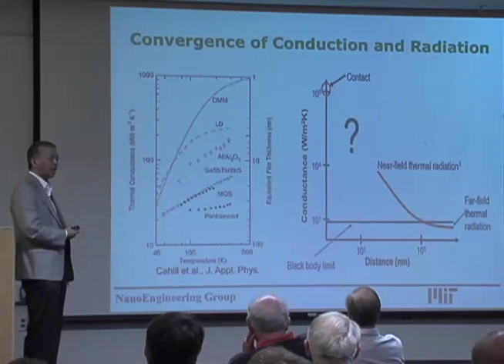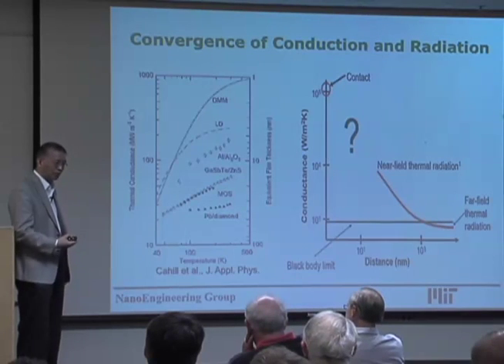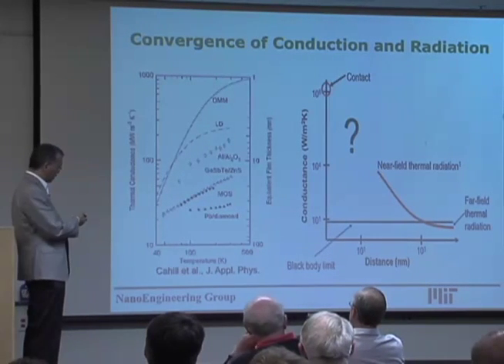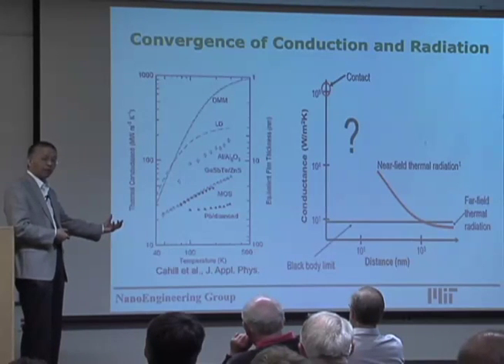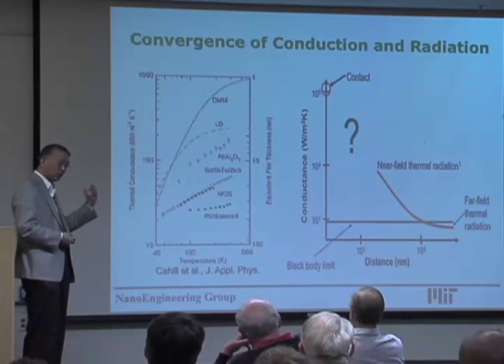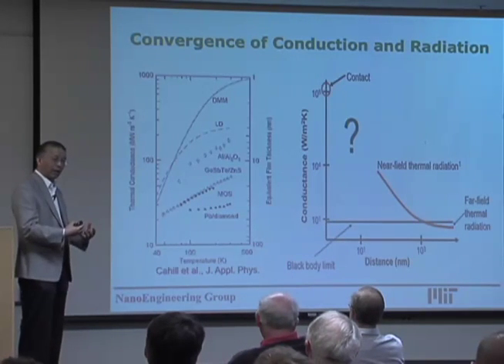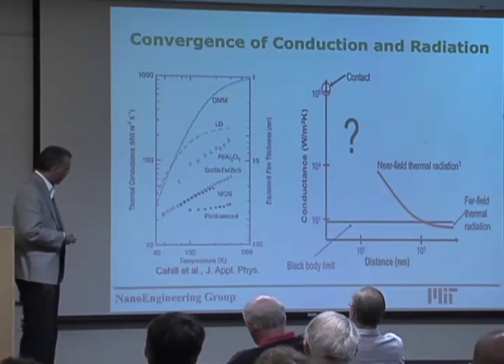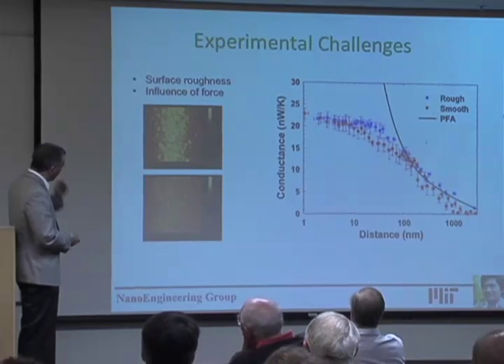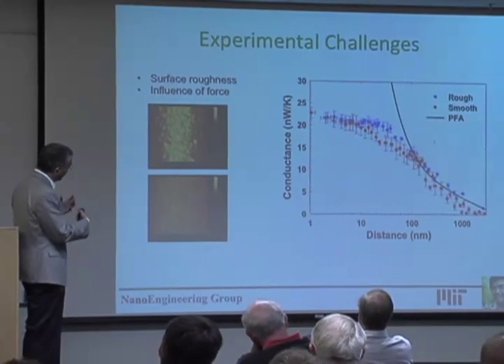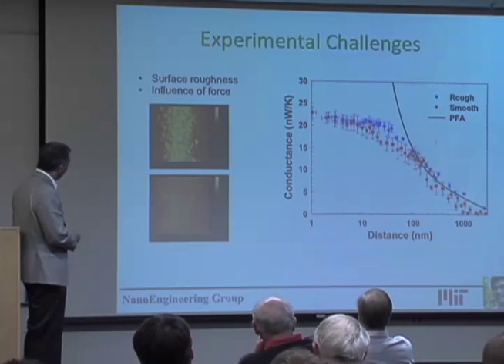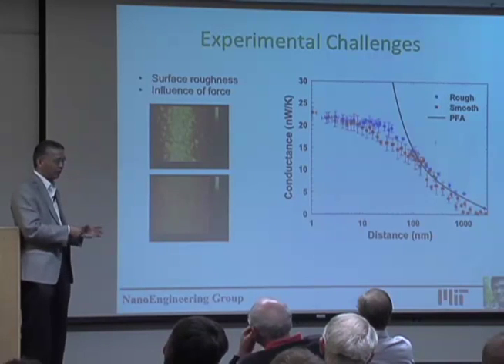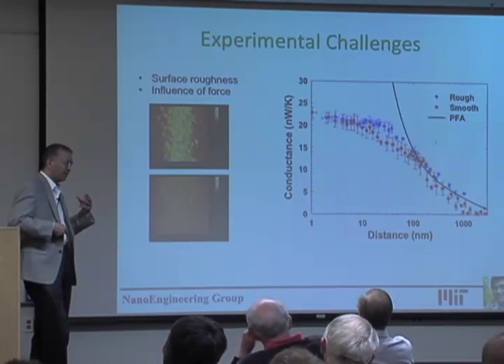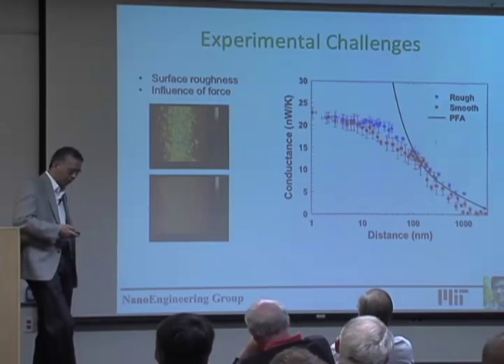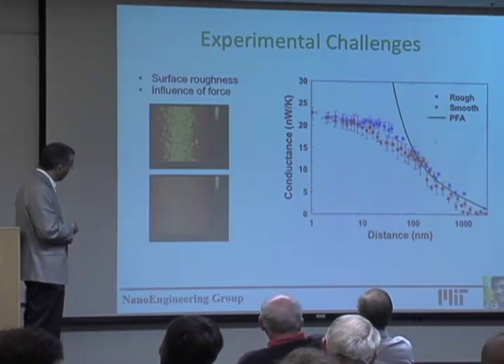It's interesting to ask, in this regime, what's the right language? What's the right picture? Because in the contact regime, we use the phonon transport picture, and in the near field, we still use the photon transport picture. How do we describe it from a basic theory perspective? On one side we're trying to push the experiment to the contact regime, and we're designing different cantilevers and doing the experiments. This is actually after 3 or 4 years of work, and we have not published it because the surface roughness has plagued us. It makes the data interpretation much more complex.